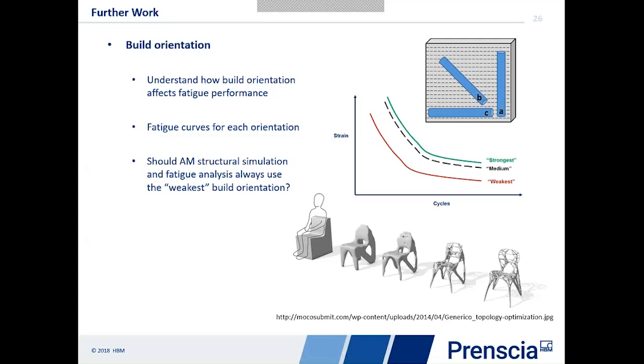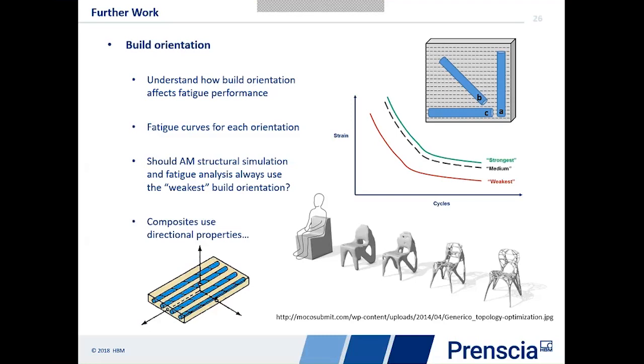Now, we do know as an industry already that where we've got areas of high stress, we very often orientate the printing of the components to make sure we have a favorable layup in those highly stressed areas. But again, what I'd like to do is quantify those effects to see how we need to model them. Of course, the worst case scenario in terms of modeling is that we treat everything as a composite, which has non-isotropic properties, so different properties in each direction. We've still not ruled that out, but so far the results are looking quite favorable.